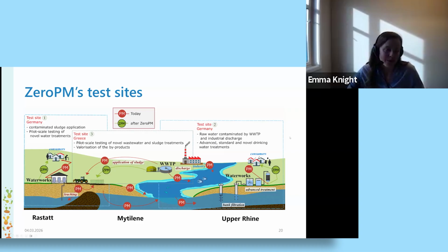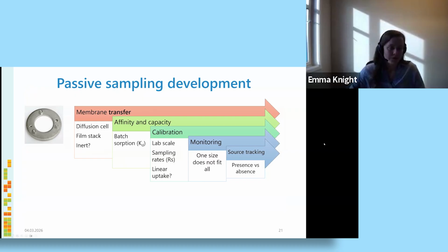So I'll talk a little bit about what we've done as part of ZeroPM with passive sampling at least one of these sites, and just show you how the results compare to typical water sampling and how we can use these measurements in the future. So for the passive sampling development within ZeroPM, we've used a polar organic chemical integrative sampler, and we've done a number of different steps to be able to optimize the sampler before we get to a monitoring stage.